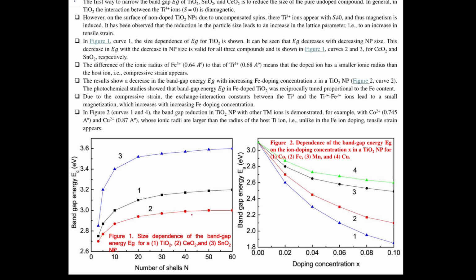When the metallic substituents, impurity ions, you can say cations, integrate into the matrix of the TiO2 material, they create impurity levels near the top of the valence band. These oxygen vacancies, or you can say the point defects, play an important role in modifying the energy levels of the conduction band.